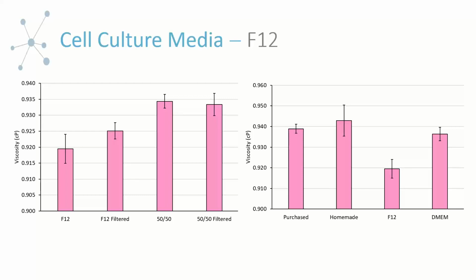So then we moved on to F12 media, and we were looking to see if there's a difference between filtering the media or unfiltering the media, and then there's also a 50-50 formulation of F12 and DMEM, and we wanted to see if there was a difference between purchased and homemade. So we took our high glucose DMEM and our F12 media, mixed them together at a 50-50 ratio, and then compared that to the purchased formulation. And we determined there was no difference between those groups, but there is a difference between the F12 and the DMEM. I believe the F12 has about 10 millimolar glucose, while the high glucose DMEM, like I said, has 25 millimolar